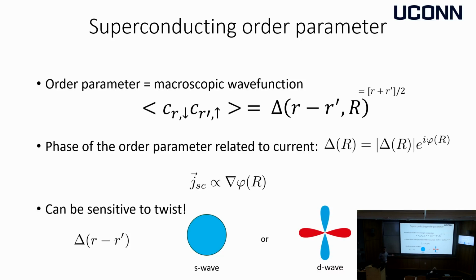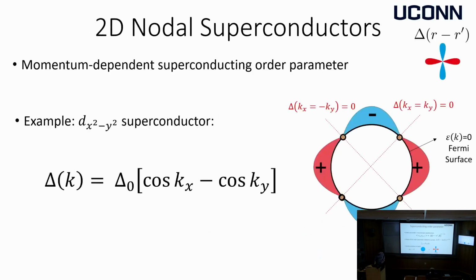Okay, so we have the superconducting order parameter. That's one big thing present in superconductors. But there's also, of course, electrons. And electrons in a superconductor, their energy is greatly reconstructed by the presence of this order parameter. So the way to understand this is to go to momentum space, where original electrons without superconductivity have some kind of a Fermi surface, and inside this Fermi surface, all states are occupied, outside all are empty, so this is the low energy manifold. Once you have superconducting pairing, basically what you end up with is opening a gap on this Fermi surface where no excitations can happen below a certain energy, and if your order parameter, its relative wave function, is sign changing, so will the sign of the gap at the Fermi surface.